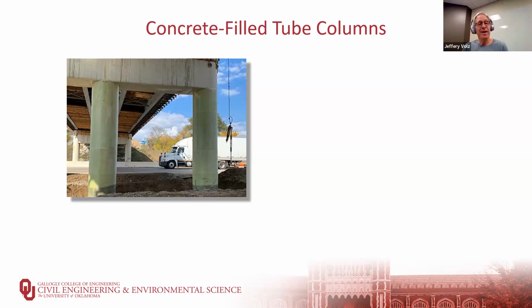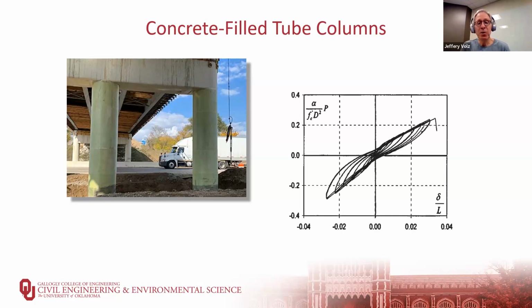So researchers and DOT officials decided, well, why don't we just build new columns with FRP tubes filled with concrete? That eliminates the problem we have with the steel-filled columns and gives us a more durable structure. Unfortunately, testing of those columns shows that they don't have as good an energy absorption. That's primarily because FRP is a very linear elastic material up until failure. So it doesn't have the ability to yield like steel does and absorb energy.